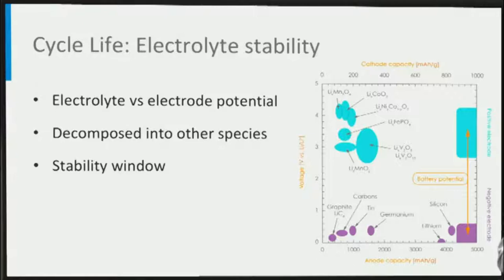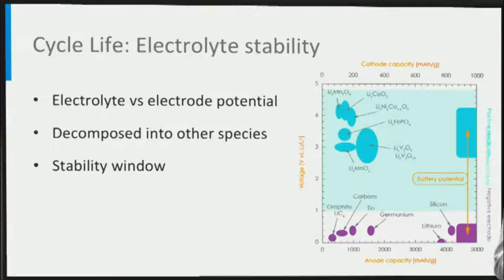For the large voltage of lithium-ion batteries, stable organic electrolytes have been developed. By mapping the electrolyte stability window on the potentials of the electrodes, we can determine which electrodes fall within the electrolyte stability window. However, it is not always necessary to have electrode potentials within this stability window to achieve a long cycle life.